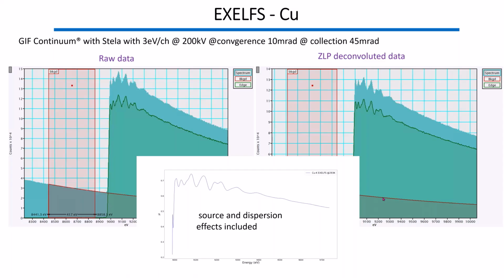Okay, the next question is, what dispersions are you using for these experiments? 3 eV per channel. We want to cover the large energy range, so we try 3 eV. If you want fine structures, you can try 1.5 or smaller, but in the single ones the main problem is counts. So basically, we just try to get enough counts per pixel. If we're using 1.5, you will probably need to do the binning later.